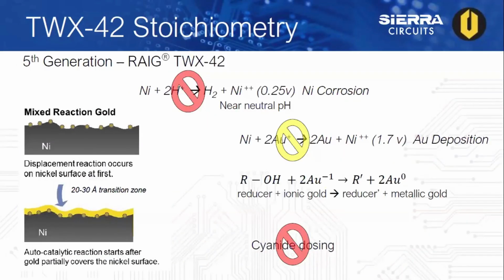Uyemura developed a newer generation mixed reaction gold bath, the TWX42 shown here. A displacement reaction initially takes place on the nickel surface, as shown in the illustration on the left. The reaction builds up 20 to 30 angstroms of gold, and then an autocatalytic reaction takes over to build the remaining gold thickness.